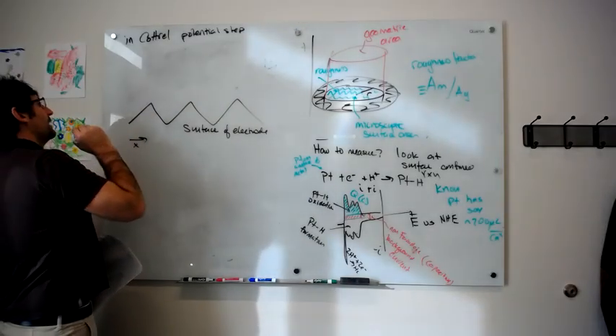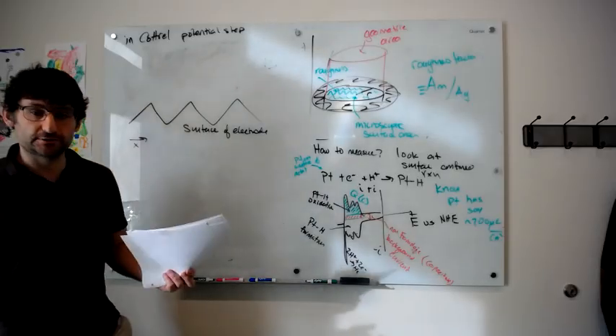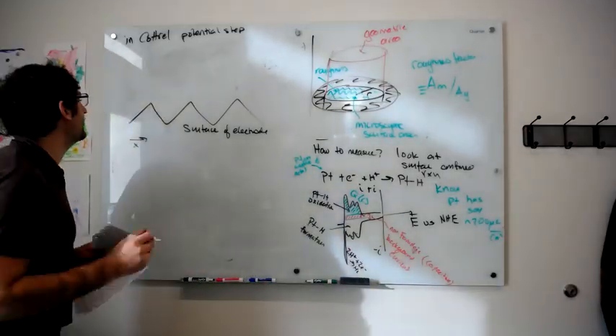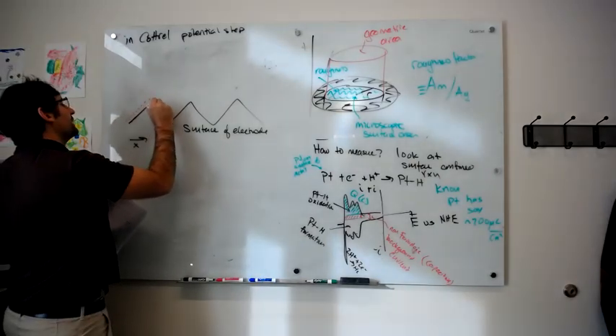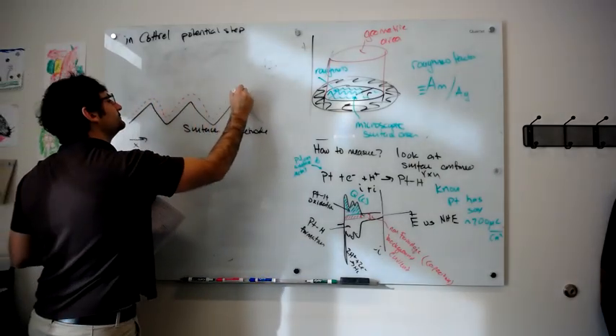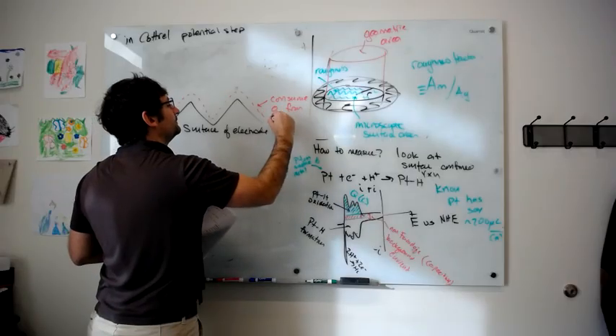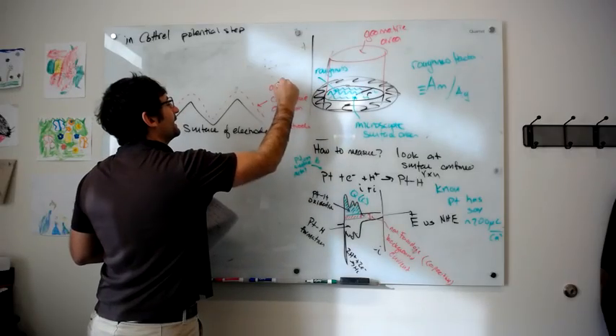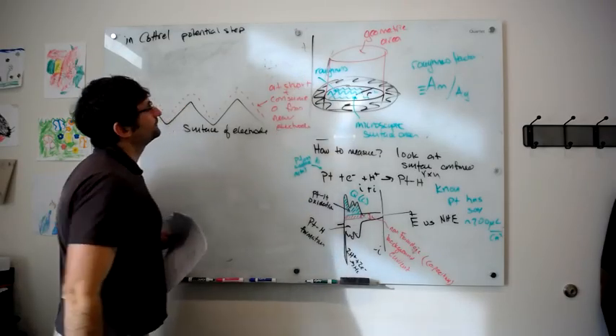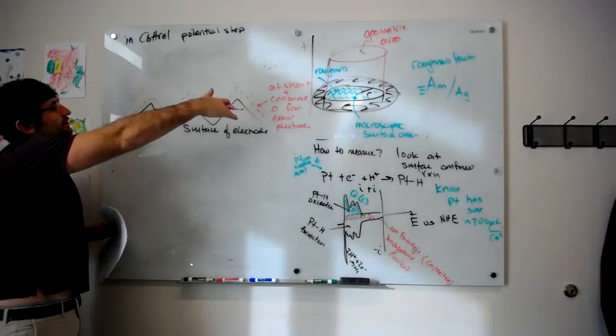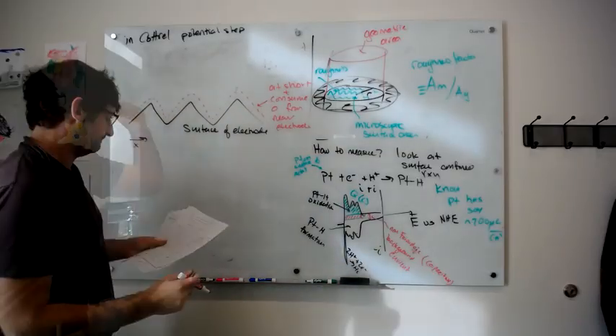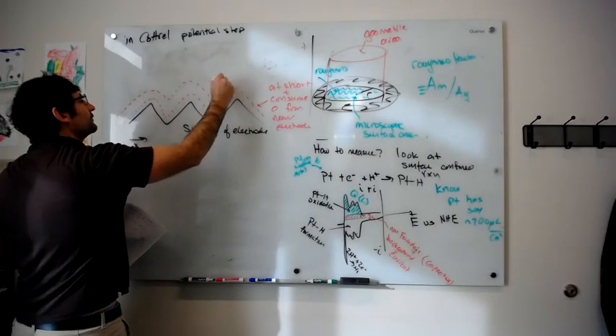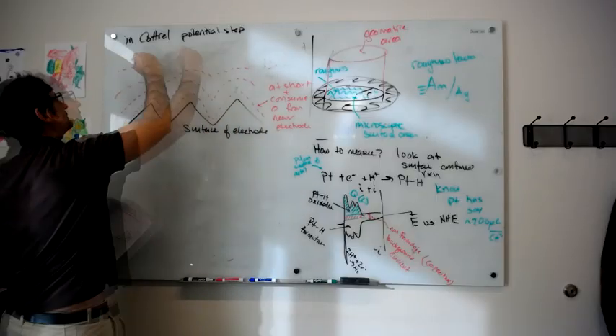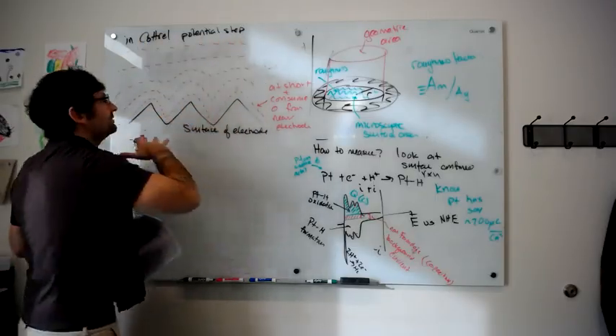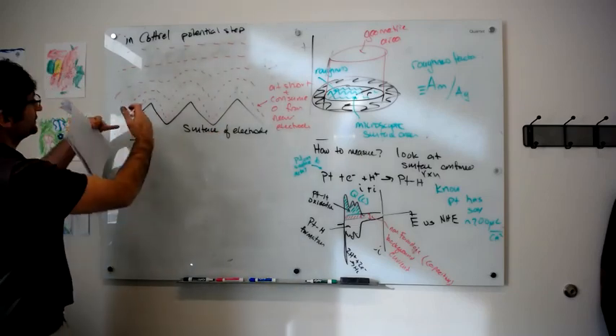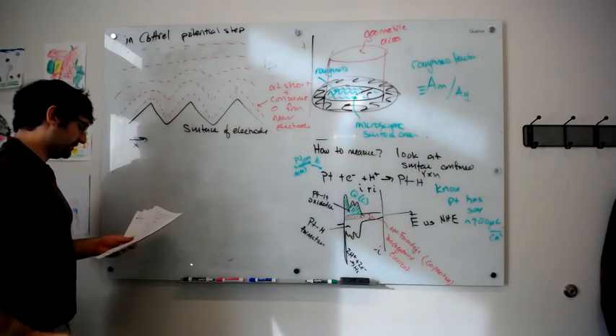So I could write contours in concentration as lines, much like you would on a topography map. Originally, at short times, I'm going to consume O from near the electrode at short t. So this is going to trace the microscopic area of my electrode. And if I keep pulling from the electrolyte, eventually these microscopic features are going to be blurred out by the overlapping diffusion fields coming from these sharp microscopic features.